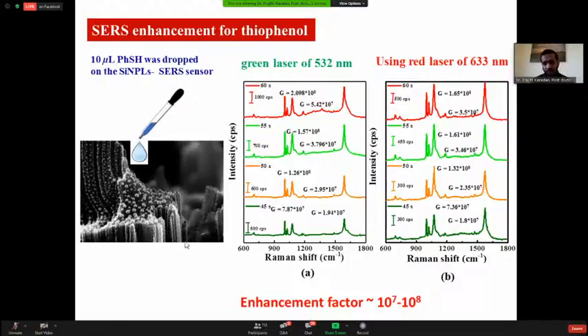So after recording the Raman, we could see that this sensor is surprisingly giving an enhancement factor of 10 to the power 7 to 10 to the power 8. We have recorded the Raman spectra using a green laser of 532 nanometer and a red laser of 633 nanometer as well. And you can see the corresponding vibrational spectra of the molecule where the intensity is much more enhanced compared to the Raman spectra.